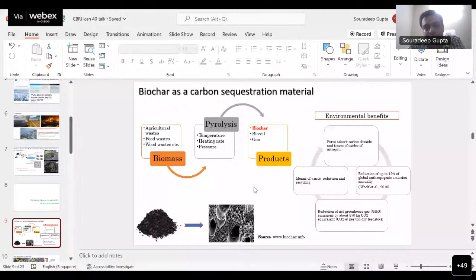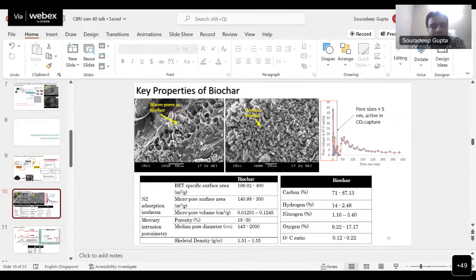So just to give you some idea of how it looks, we can get a feel of how the whole mechanism of carbon capture takes place in the pores of biochar. If we look at it under SEM, we can see a lot of these macropores, which are inherited from the vascular structure of the plant body. But we can very easily grind it into very fine particles or make it a very fine filler, which is desired for use in cementitious composite. Although we cannot see a lot of pores in this, these particles contain a substantial fraction of micro and mesopores less than 5 nanometer. And these pores are super active in capturing CO2 and storing it through adsorption when put in building materials.